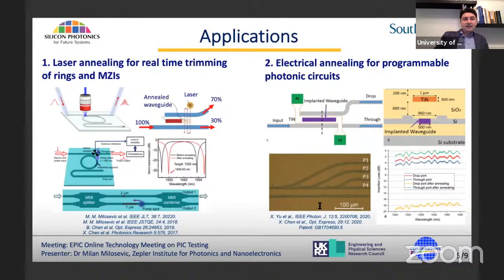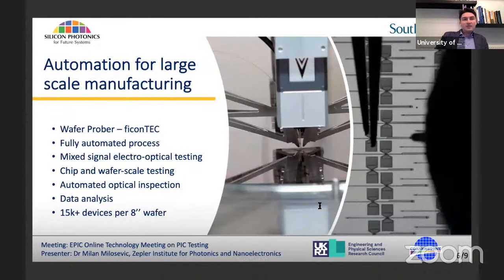more about this. In terms of automation, we have been working for a few years with ficonTEC to bring this technology from lab to practice, and we have developed a wafer prober, which can be used for mixed signal electro-optical testing, for chip and wafer scale testing, for automated optical inspection of the wafer, data analysis, and so on. We managed to test a lot of devices on the 8-inch wafer. And here in this image, you can see both optical and electrical probes positioned on top of our 8-inch wafer.